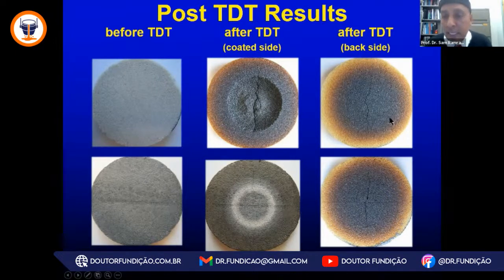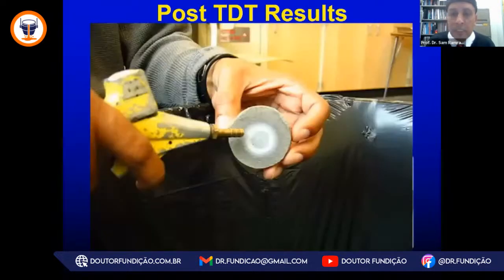If you look on the back side of the specimen, we are measuring the temperatures, but you can see the same amount of pyrolysis and you see the crack. So you know the heat is getting through. The coating in this case is protecting the mold metal interface from maybe defects like veining or penetration, but it is not preventing the casting from distortion or displacement.